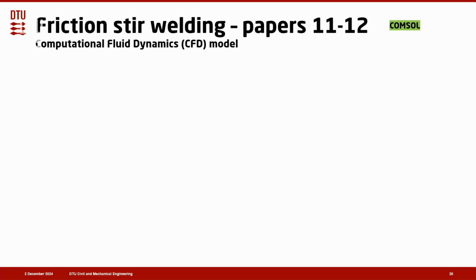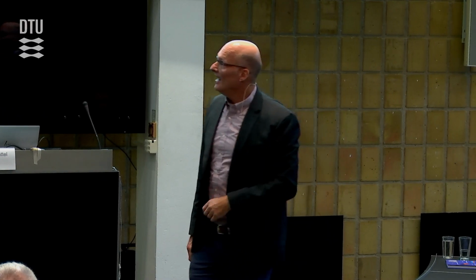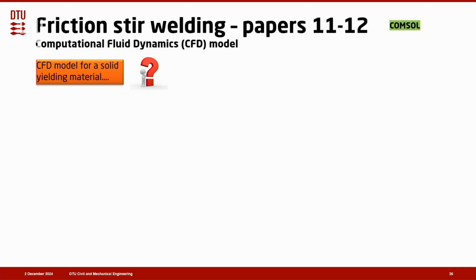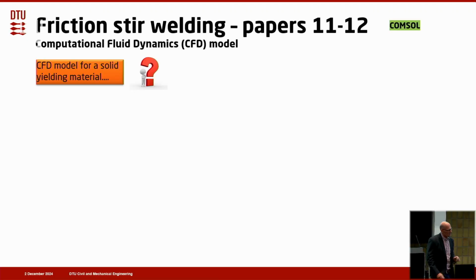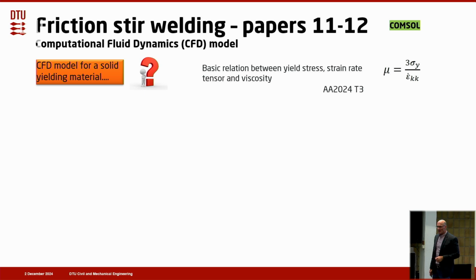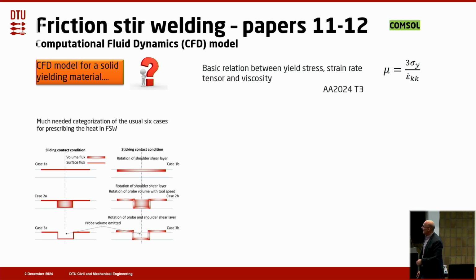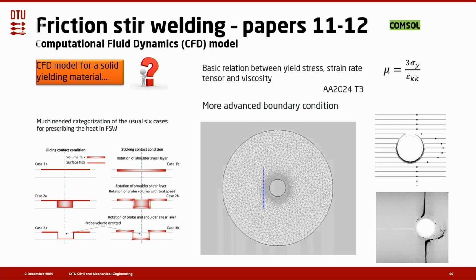Then we did a CFD model. CFD, computational fluid dynamics, it's something with flow, right? And you might ask yourself, how can you make a CFD model for a solid yielding material? It's not flow. Well, it is flow in the sense that it's so soft that it flows. And we go about the basic relation between yield stress, strain rate tensor, and viscosity. And then we also made a very much needed categorization of the different ways of prescribing the heat generation in friction stir welding. And here you see a simulation.